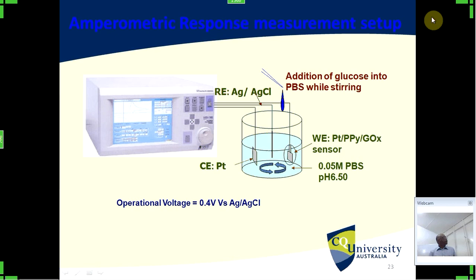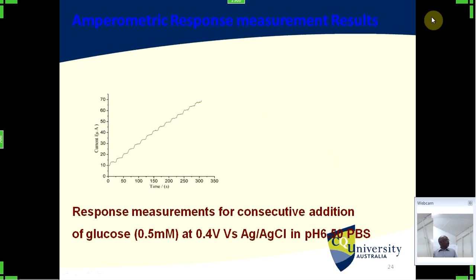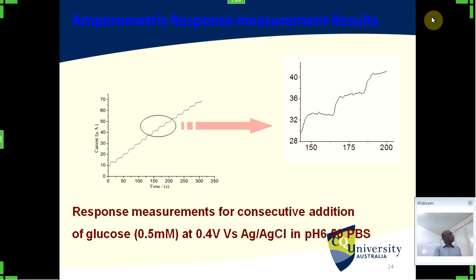And we added glucose into this phosphate buffer solution in known amounts and measured the current with respect to time and recorded that. 0.5 millimole of glucose into the solution. This voltage was set by previous experiments on cyclic voltammetry, basically to get the best operating point for the reaction. So we get an instant jump in the current. These are the points where we added the glucose into the solution, so you get a very quick response and it's getting stabilized.